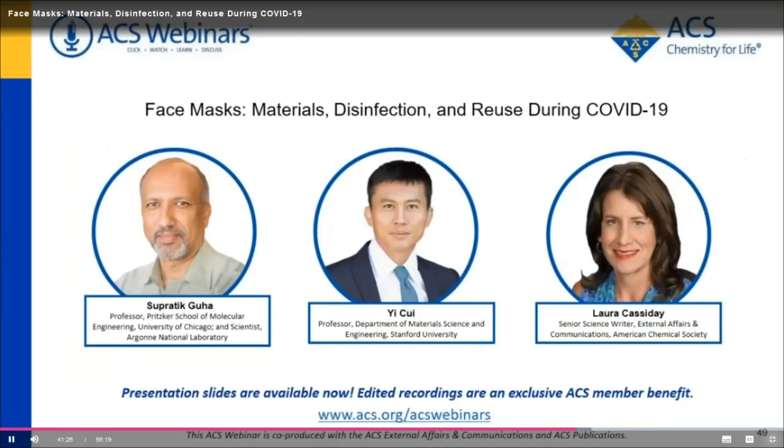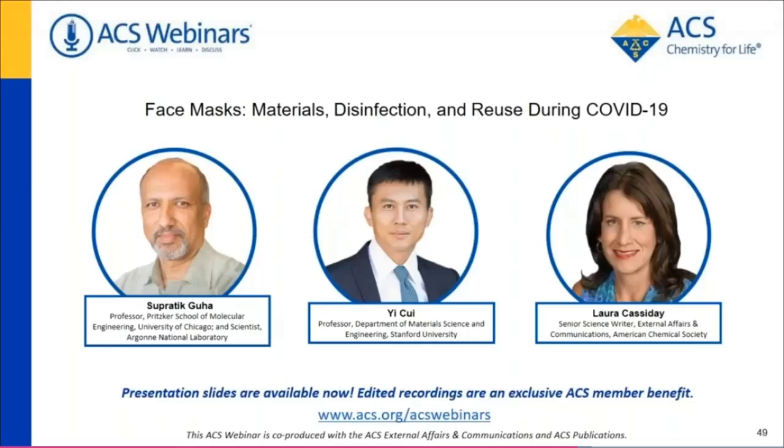That's a good question, and these are the kinds of things we are beginning to look at. So I don't know the answer for sure. My guess is that, given these are acting as electrostatic filters, they can be negatively impacted by humidity. In that case, I would suggest keeping the chiffon or the silk on the outside instead of towards the nose. On the other hand, what we're also seeing is that if there is humidity, the fibers swell up somewhat, and in some cases the efficiency can actually increase. So it's not clear whether that makes a difference at all, and if it does, to what extent in the net, but this is something we need to look at more carefully, and we are.